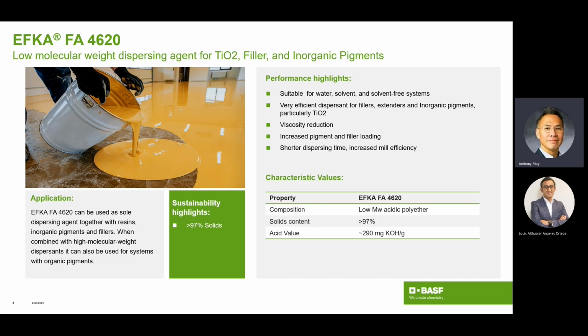And when you use this dispersing agent, you're going to have very good viscosity reduction as it stabilizes the pigment particles. Along with that, you will have the opportunity to increase your pigment and filler loading to further enhance your mechanical properties. And at the end of the day, you'll have shorter dispersing time with increased milling efficiency. So EFKA FA4620 is what I would recommend for dispersing inorganic pigments in a very efficient manner.